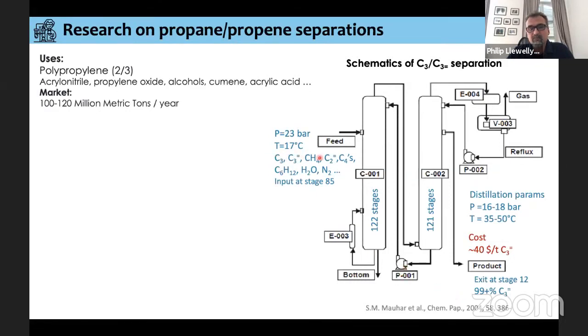So just to give you an idea, I've taken this from the publication here. We have propane, propylene, and many other different molecules coming in at 23 bar and at a little bit below room temperature. Then we have a distillation, which in this industrial setup is with two large, very high columns. It's too high to have one big column, and each of these has different stages, around 120 stages for each column. The product comes out at over 99% purity.